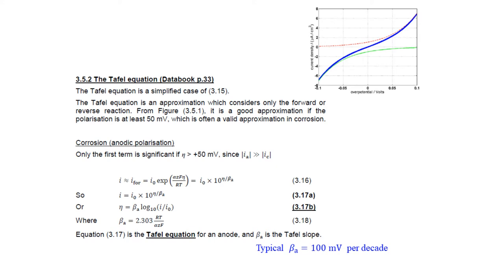And if you look up the anode Tafel slope, or if you evaluate it, if you're given the fundamental parameters, then you get the beta a term, and you can put it into the Tafel equation to predict the current density affecting the metal surface. I can get that as equation 3.17a, the Tafel equation. Or I could rearrange it, and say that the polarization, the anodic polarization, is this Tafel slope beta a times the log base 10 of the actual current over the exchange current density. Okay.